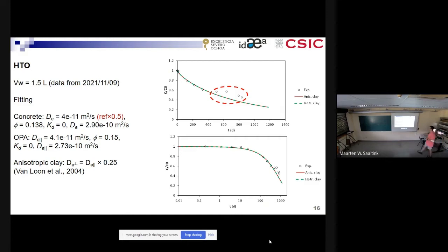And here, this is just to highlight the fact that we have this deviation after long times. I mean, we have a perfectly nice diffusion curve, and after 500 days or so, we see a deviation. I think this is expected to be an effect of an influx of water, actually. I think there's a pattern that is not so tight, so there's a little bit of water going into the interval along that pattern. So that is probably the reason for that deviation.